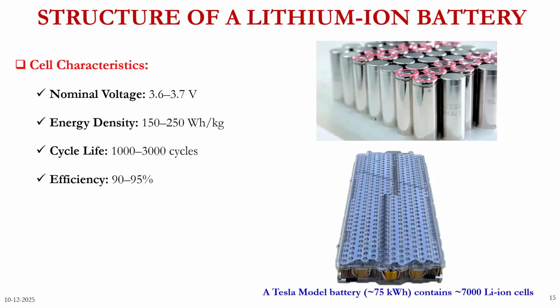And if you charge your battery continuously, especially lithium ion batteries, there is a chance that the battery performance may degrade. That is, the number of life cycles, which is almost 3000 cycles, will come down. So how to use your lithium ion battery? Whether it is your mobile, a laptop, or an electric vehicle, any lithium ion battery, you should start charging it when it is at 20% SOC, and you should charge it only till 80%. You should not always go to 100%. So 20% to 80% should be your charge discharge range.